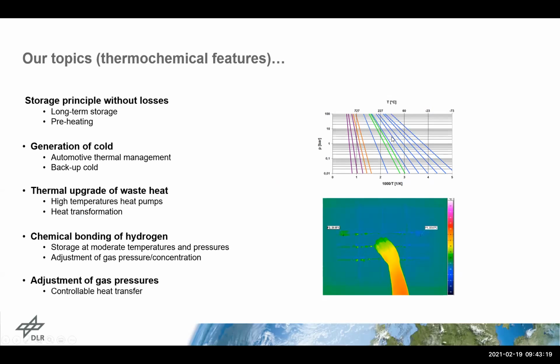Since we can have hydrogen as reaction gas here, we try to find synergies between hydrogen as energy carrier and hydrogen as a reaction gas for these thermochemical systems. This is of course important in order to reduce the complexity of the later complete storage unit. And we have some topics where we do not try to adjust the reaction temperature, but where we try to adjust the pressure, so the y-axis, for instance, in order to control the heat transfer through vacuum panels or something like this. Why am I saying that?